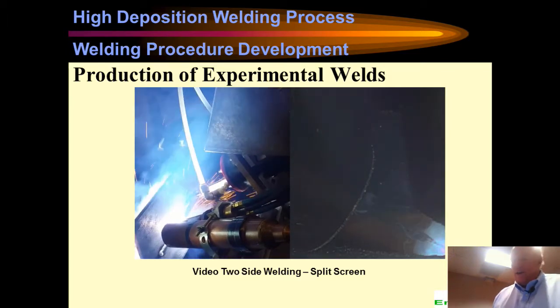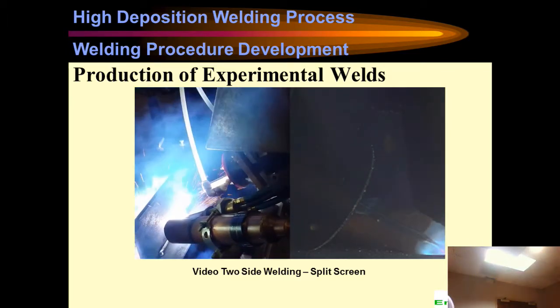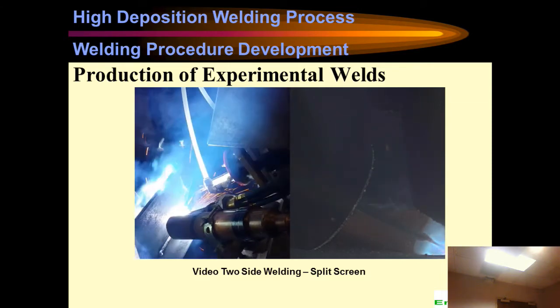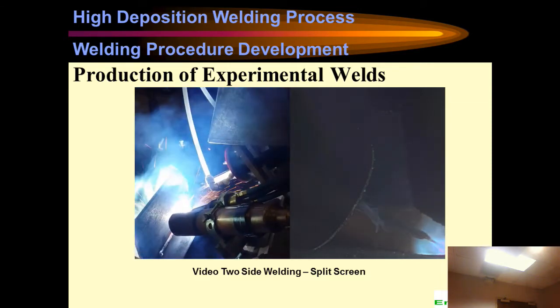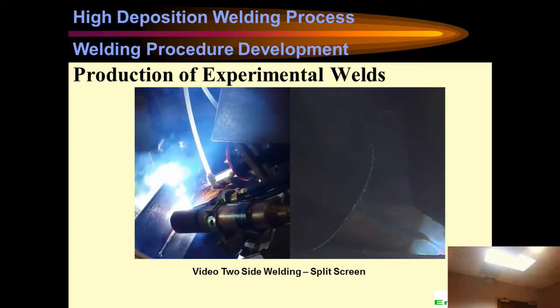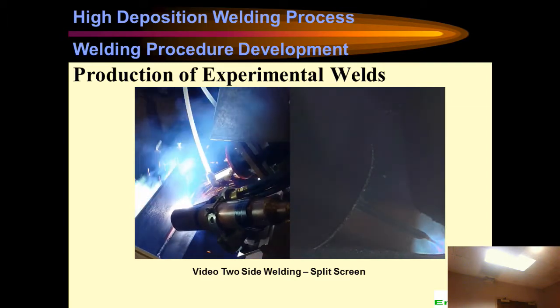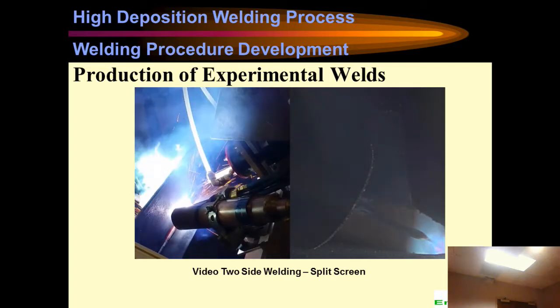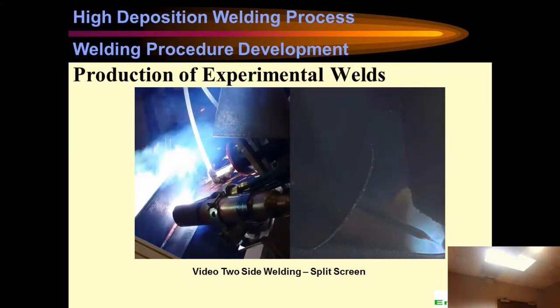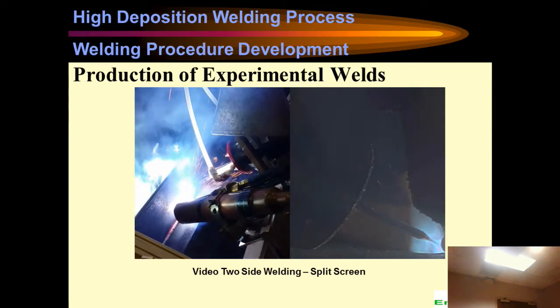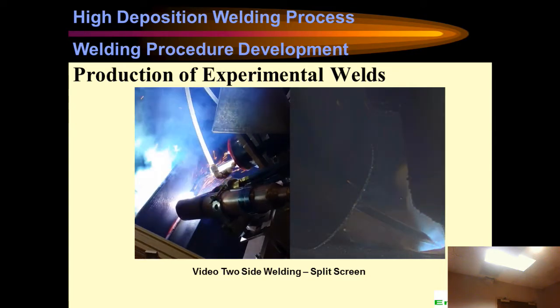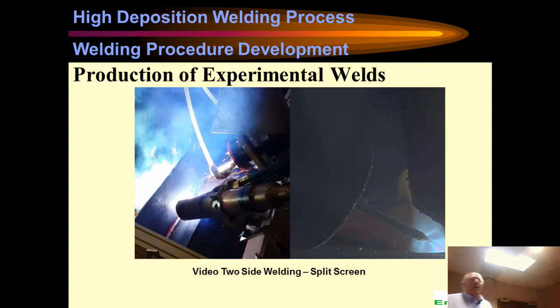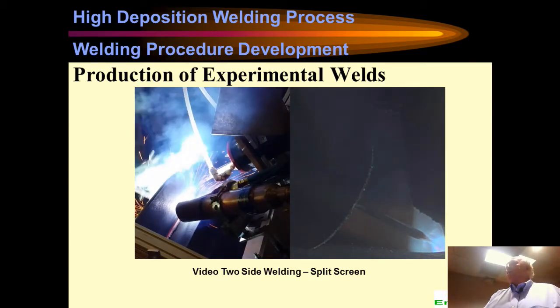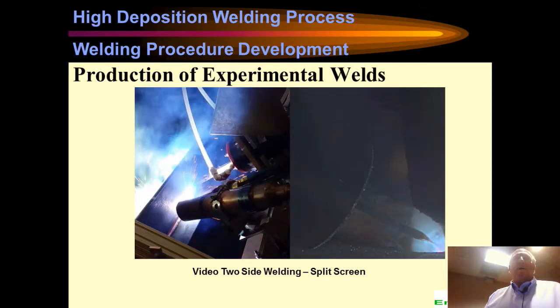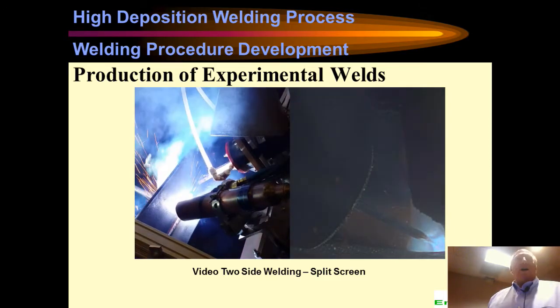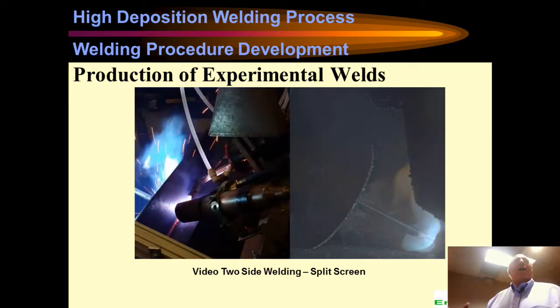And the interesting thing here is because the metal is up at the melting point, the arc is actually sort of machining its own joint. So you'd like to have a J-groove, that's always perfect, but nobody can ever afford to machine J-grooves. But the arc is actually machining a J-groove that's exactly the right size for that arc, all by itself. So that's kind of one of the neat things we found. We have this camera outside, by the way, if anybody wants to take a look at it. Visible Welding just came out with this camera, and you can see not only the arc, but all the surroundings using this camera.